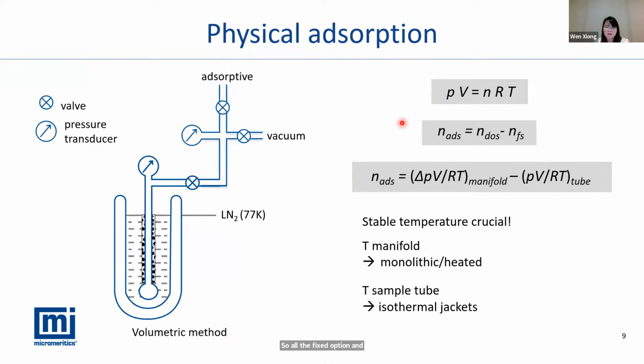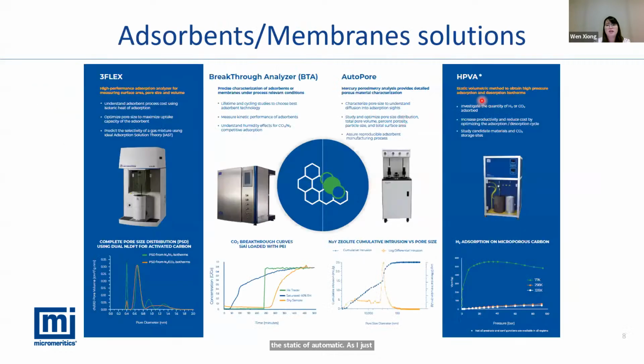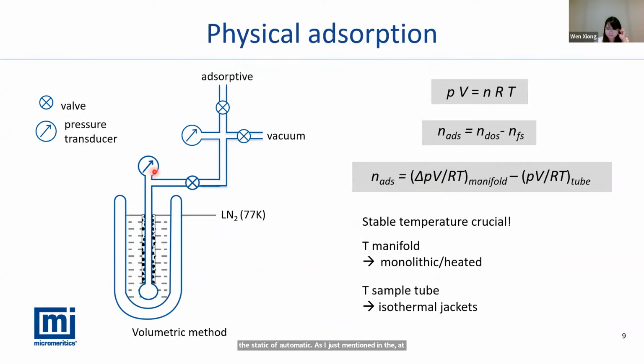So for all the physical adsorption measurement in Micromeritics, we are using the static volumetric method, as I just mentioned in the HPVA and the 3FLEX working principle. The static method is measuring the adsorption pressure change during the adsorption process. Then we use the mass balance equation and the gas equation of state, and with the measured pressure, we do the calculation. And then we get the gas adsorption amount, the pore size or pore structure, and using different models we also can get the pore volume, pore size, and the surface area.